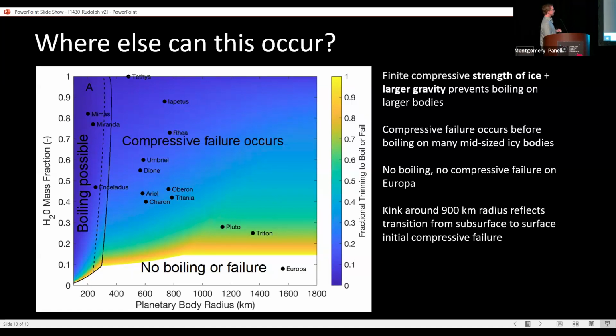On larger icy bodies, before ocean underpressures low enough to initiate boiling can be achieved, compressive failure occurs within the ice shell, and this limits further decreases in the ocean pressure. You can see that there's a kink in the bottom part of this chart around 900 kilometers radius. This actually reflects a transition from compressive failure in the subsurface to compressive failure at the surface of the planetary body. The third possibility is that neither boiling nor compressive failure of the ice shell is possible. And Europa stands alone among all of the icy bodies in that this process cannot drive either compressive failure or subsurface boiling.